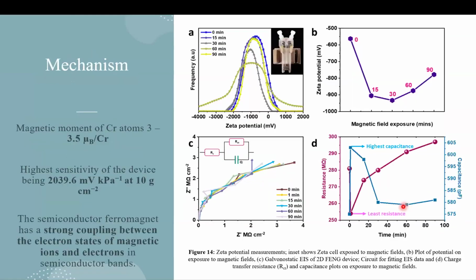So the mechanism of what is happening inside these particles is that on application of external magnetic fields, we see that the charges in the tellurides are being disrupted, and until some exposure of magnetic field, we are able to see a stable charge distribution when measured with zeta potential. And we also did EIS measurements, and we were able to see that on exposure to magnetic fields, the charge transfer resistance in the material actually reduces.